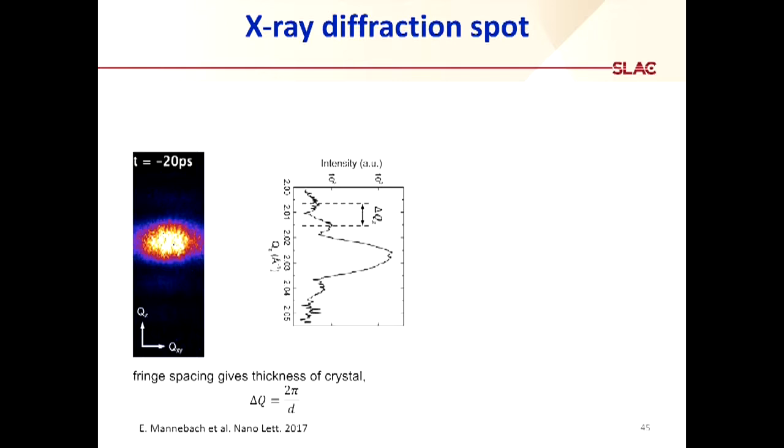All right, so it turns out that this is a very nice diagnostic because it's actually a reflection of the fact that we're looking at a thin film. The Bragg criterion that I described results from taking the Fourier transform of the crystal structure of infinite scale, and then you get rigorous momentum conservation. When you have a sample of finite thickness in the z direction, then you really have crystal truncation rods, and you have a relaxation of exact momentum conservation. These extra fringes reflect the number of layers of the crystal in the vertical direction. So that turned out to be very convenient. We could exactly characterize the thickness of the sample.